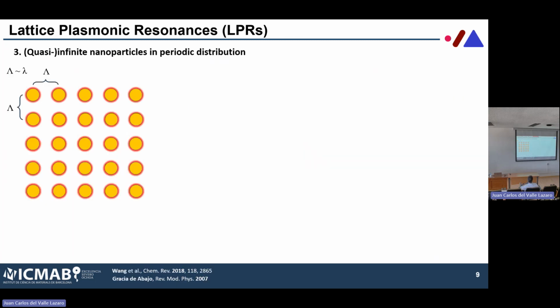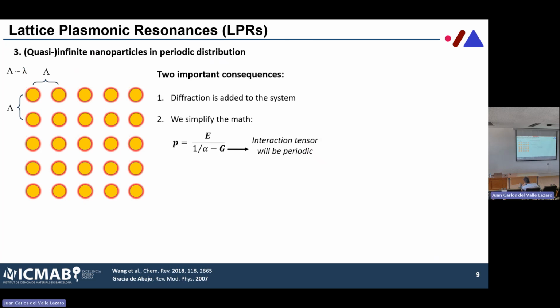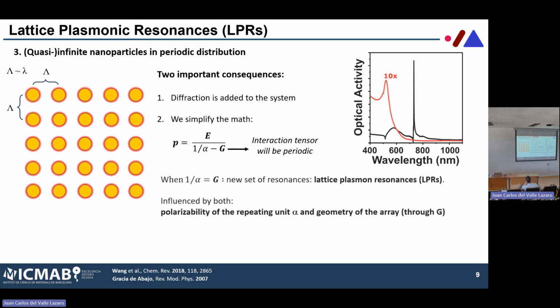However, if we look at a system where the nanoparticles are organized in an array, then things change a little bit. So the first thing that is a very important consequence is that we can simplify the math, which I always appreciate. So we can basically get to this kind of equation where we see that the conditions for the resonance, so for a maximum value of this number here, are found when the polarizability and the tensor have a specific relation, they're basically similar one to the other. And this is a new set of resonances, because they do not only depend on the polarizability, but depend also on the lattice, so on how we dispose these nanoparticles in 2 dimensions.